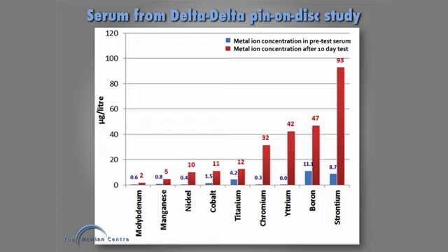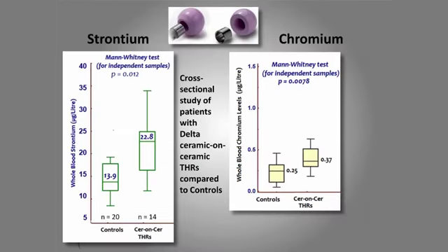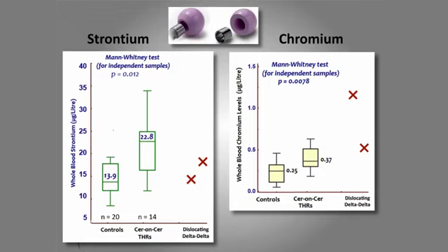So Delta-Delta doesn't produce metal ions? I don't think so, not on the basis of that pin on disc test. Here's a clinical study that we did, a small cross-sectional study with 20 control patients, pre-operative patients with no metal in them, and 14 Delta-Delta total hips, all above 1 year, who were all functioning perfectly. And we measured their blood strontium and chromium concentrations. And even in this small cross-sectional study, there is a significant increase of both chromium and strontium in the Delta-Delta patients. Interestingly, these are strontium and chromium levels in the blood in 2 patients who had dislocating Delta-Delta total hips.